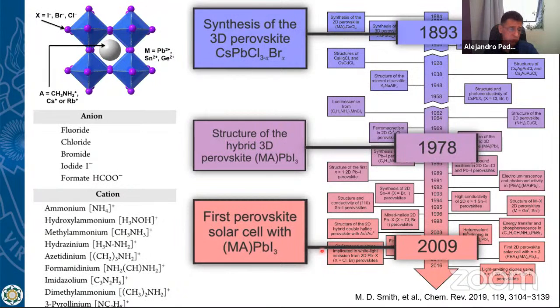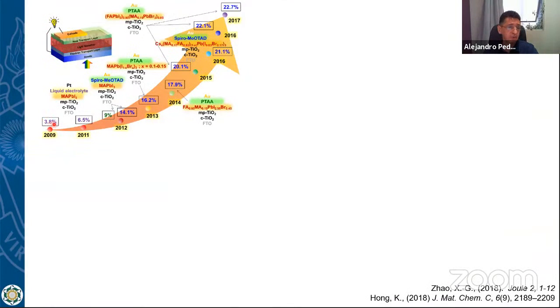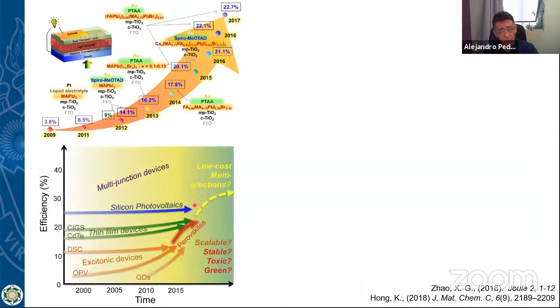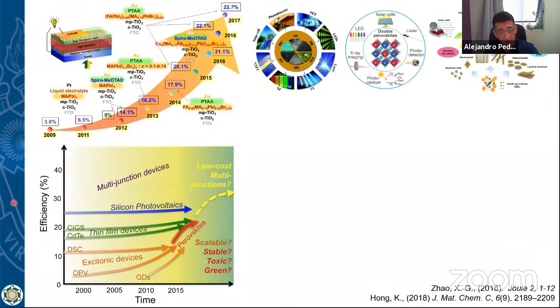It was a quite poor solar cell, with a quite poor efficiency, 3%, but with further development, they reached around 22%, around 20% in 2015, and with that, the research in the field really exploded because we are reaching now nearly 30% efficiency with a perovskite, which is above the traditional solar cell.